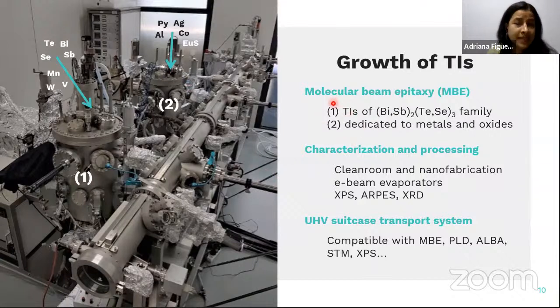For that we use molecular beam epitaxy, using this machine that I'm showing here in the picture. This is a very nice machine because we have two chambers to have a controlled growth of the materials. One of those is dedicated to the growth of the TIs. In this case, we have evaporation cells for bismuth, antimony, tellurium, and selenium. We have other transition metals here for doping or for growing other systems. And then we have a second chamber, which is dedicated to metals and oxides. And the nice thing is that we can grow samples in both chambers and then transfer them in vacuum through this vacuum tunnel that we have here, so that we can grow heterostructures, including TIs and other, for example, magnetic materials or metallic materials here.